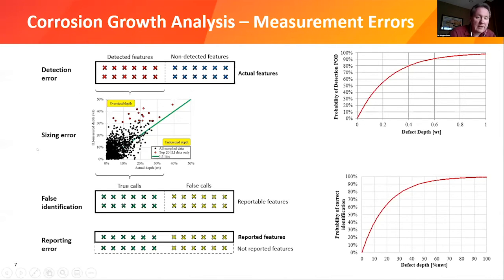We then also have identification errors, that we think, okay, this is a metal loss, or it's a different feature type and it's not classified as a metal loss. Those happen as well. And then the ILI vendors usually cut off very small defects and don't report all of them, simply because the errors on the very small ones are so large that they say, okay, they're not very important, we just leave them out. So based on these lists we saw earlier, that are obtained from the ILI vendors, before we can actually determine the corrosion growth, we have to consider all of these effects before we can do the analysis.